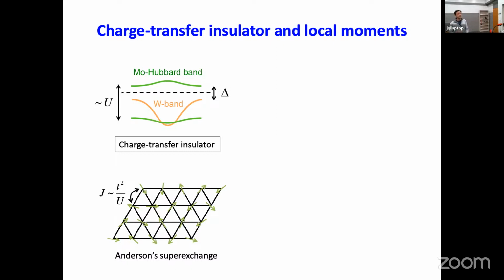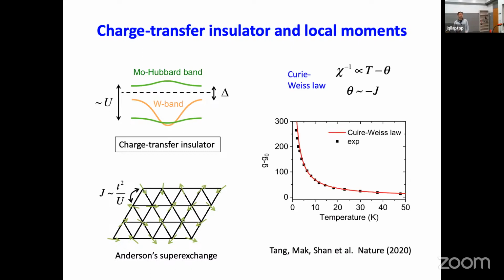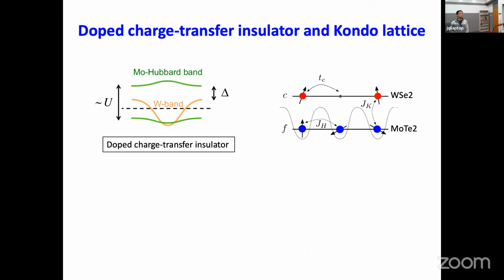Okay, and you can actually really see the effect of the presence of this triangular lattice of local moments by measuring the temperature dependent magnetic susceptibility. You can see that it follows very nicely the Curie-Weiss law, which is really the signature of the presence of a lattice of local moments in the system. And in fact, by fitting to the Curie-Weiss law, you can also get a measure of the exchange energy scale in this kind of system. So it's at least consistent with the Anderson super exchange, which is anti-ferromagnetic. We have a negative Curie-Weiss temperature in this system.